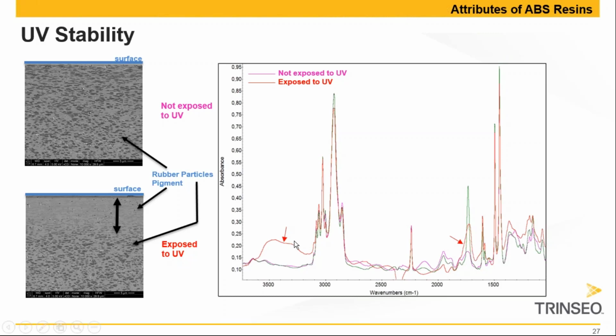Second, more to the left side, you see this peak appearing between 3,200 and 3,500 reciprocal centimeters. And this is typical for the nitrogen-hydrogen stretching vibrations for amides. And also these are formed during the photodegradation of SAN. Now, the photodegradation process of SAN also causes the formation of yellow bodies, leading to color changes, and next to that, it also leads to the reduction of the SAN's molecular weight, which then will also lead to loss in mechanical properties.